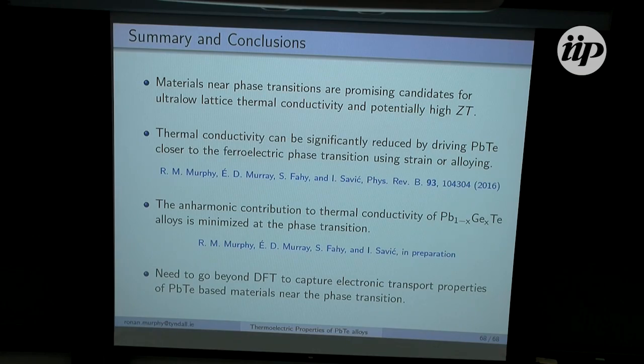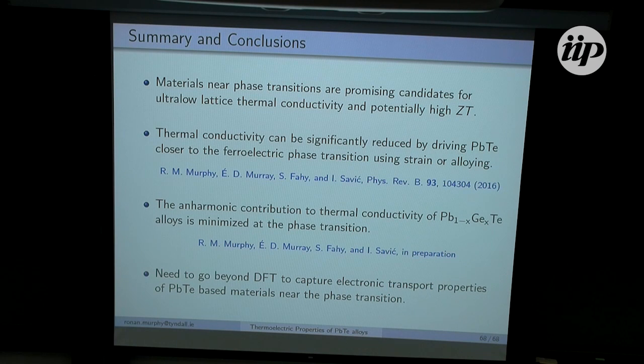Okay, so now to finish up. When we look at the literature, we can see that these materials near a phase transition look to be quite promising candidates for ultra-low lattice thermal conductivities and hopefully potentially high ZT. I show that by pushing the telluride towards the ferroelectric phase transition, you can significantly reduce the lattice thermal conductivity, and in particular, in germanium telluride, the anharmonic contribution to thermal conductivity is minimized at the phase transition.